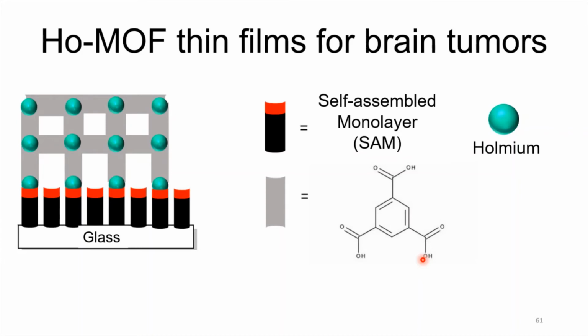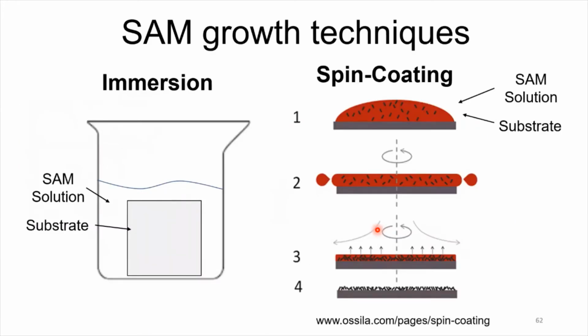And how these thin films are usually grown is through self-assembled monolayers. So you have your substrate, and you need some type of, similar to what we did with the magnetite, some type of anchors. Then with that anchor, you get your holmium or your lanthanide salt and your linker, and that's how you grow the MOF film on top of this. And James has been working at this for about a year.